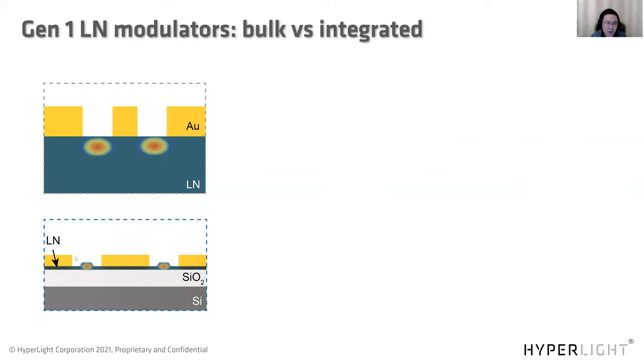And the approach thin film lithium niobate takes is very similar to the silicon on insulator platform. Instead of silicon on top, you replace that with a lithium niobate waveguide. And these waveguides are typically on the order of a micron or less, so it's a very close size to silicon. And the refractive index is about 2.2, which is very close to another popular platform, silicon nitride.